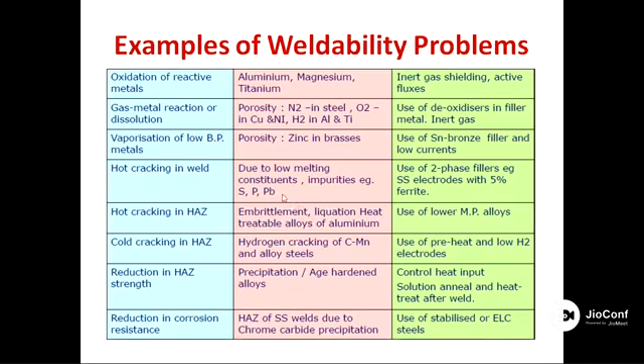So what happens? They segregate at the grain boundary, and during cooling we will see that the grain boundary shrinks because of the cooling stresses. So there will be separation of these grains where the low melting point constituents are segregated in the grain boundary. So that results in cracking. So we have to use a two-phase filler metal for stainless steel, an electrode with 5% ferrite. I'll come to this. What is the benefit of using the 5% ferrite, or what is the role of ferrite in the welding of stainless steel?